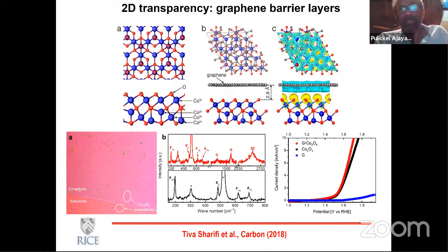And even recently, a group from MIT showed that you could even get epitaxial growth with a barrier layer or an intermediate layer of graphene sitting on the substrate, which is quite amazing, because if you can do that, then you can create super thin layers of another material on a substrate and just simply peel it off because you have this graphene layer in between. So I think extreme thinness brings some uniqueness to these materials.